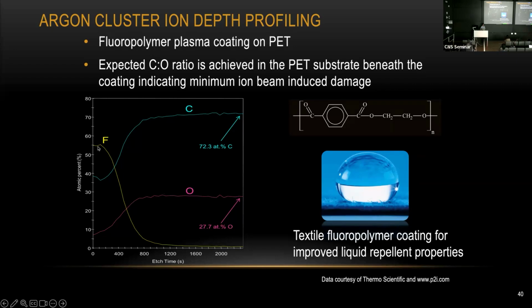Right at the beginning, you see there's a lot of fluorine signal and some carbon and some oxygen here. And after almost 400 seconds of etching, you can see the fluorine started going down. Eventually, we're seeing just carbon and oxygen, which means we reached our PET substrate here. So all the coating has been removed. So you can also use the cluster source for etching for depth profiling, and that'll be very useful for this kind of very delicate sample and delicate coating thin film.